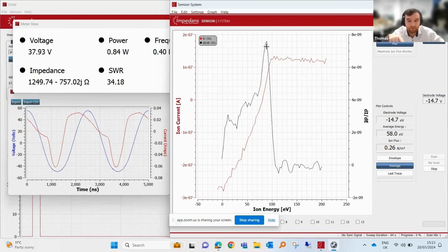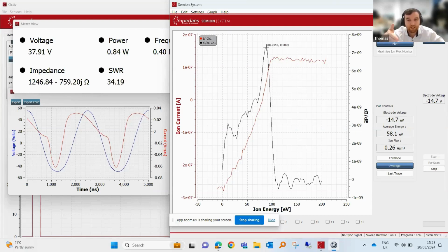You can see a peak at around, what's that, 80 eV? Yeah, 88. And then there's another peak down near zero, probably a bit above the plasma potential, something like 10 or 15 eV at the lower end. So this is your bimodal IEDF from 400 kilohertz. We're operating at about 2 pascals, so we're a little bit on the collisional side. But anyway, this is an IEDF with a sine wave.